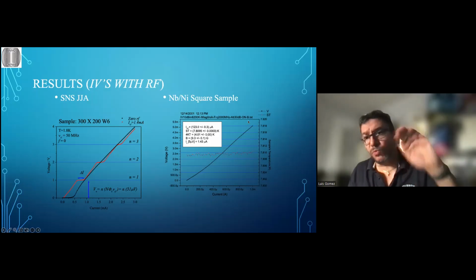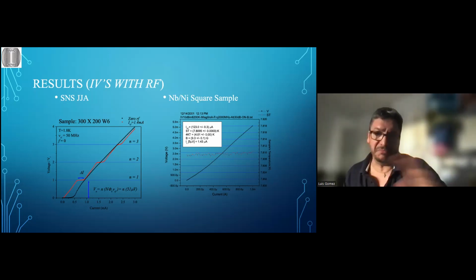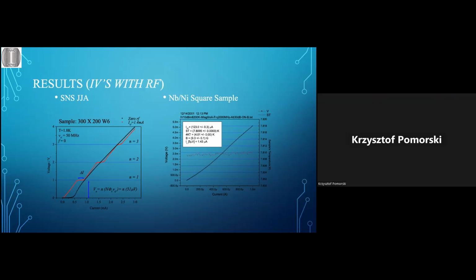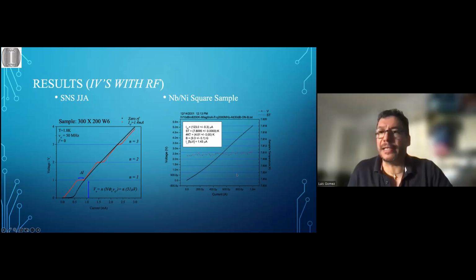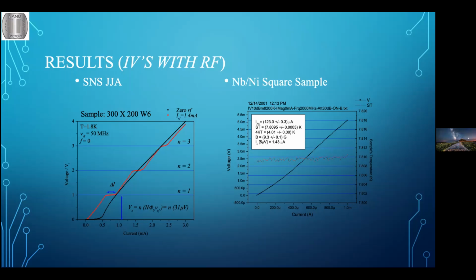One system will show Shapiro steps very clearly. The other, I don't see anything. Yes, this is about Shapiro steps. Exactly, Shapiro steps correspond to the frequency of the signal. Then, in the case of a more complex wave function with multiple frequencies, would this create a situation with multiple Shapiro steps? Well, it depends on the system. Yes, on the nickel system, you have a very non-linear response. It's not a classical Josephson junction system.